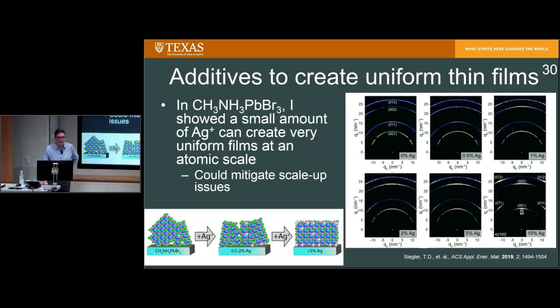One thing that we did in our lab to try to maybe help this out a little bit was another paper I recently published, where this isn't an alternative to spin coating, but I was able to add a little bit of silver to methyl ammonium lead bromide perovskite and show that I could, in so doing, create thin films that were atomically very well ordered. All the crystals were pointing in the same direction, which is kind of hard to do. And so hopefully this could help mitigate some of these issues, though it won't necessarily solve them.